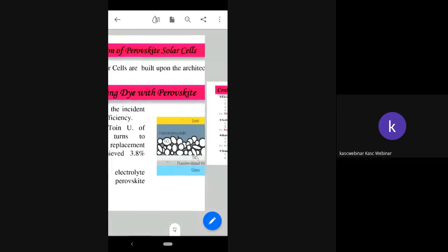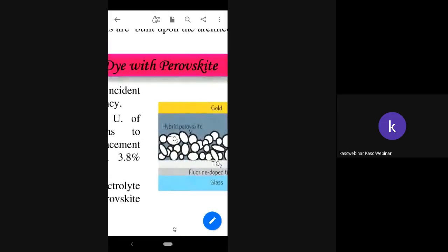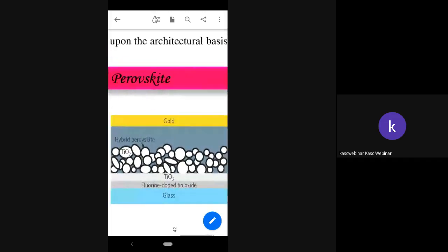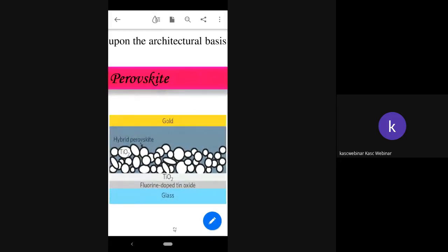Dyes do not absorb all the incident light, reducing efficiency. Still, the quest for high efficiency with long-term stability leads to the evolution of perovskite solar cells. And this type of solar cells use the same architecture of dye-sensitized solar cell. This you can see in this diagram. This is basically based on the dye-sensitized solar cell. And in 2009, perovskite turned up as a possible replacement of dye, but the liquid electrolyte dissolved the perovskite within minutes.